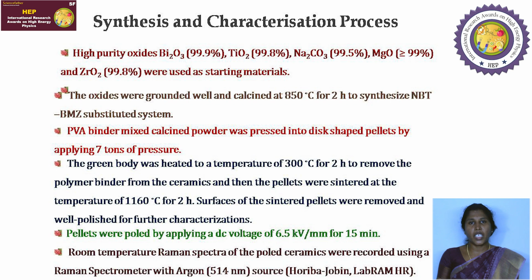pressed into pellets by applying a pressure of 7 tons and then kept in the furnace. The PVA binder is removed by heating it to 300 degrees centigrade for 2 hours. After that, the temperature is increased to 1160 degrees centigrade for 2 hours for sintering. After sintering, the sintered pellets are taken out after cooling the furnace. Then the surfaces of the sintered pellets are well polished,